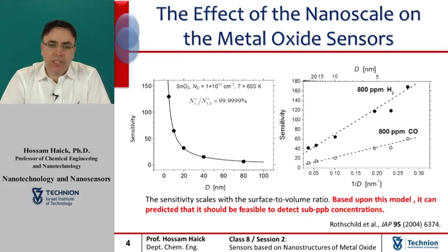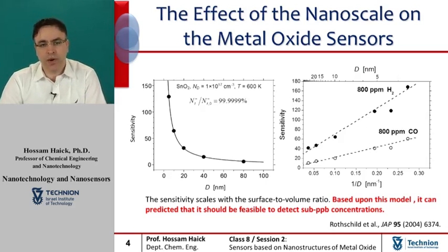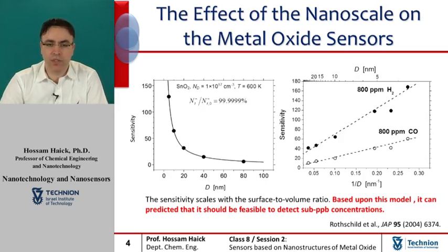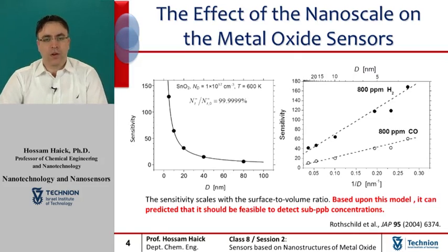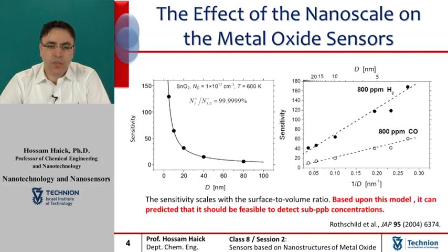In order to examine this effect quantitatively, researchers calculated the effective number of free carriers in the limit of fully depleted grains as a function of surface trap density using this integral equation, which simply follows from charge conservation. So the researchers calculated sensitivity, which is simply the ratio between the effective carrier concentrations for slightly deficient and fully saturated surface trap densities as a function of the grain size.